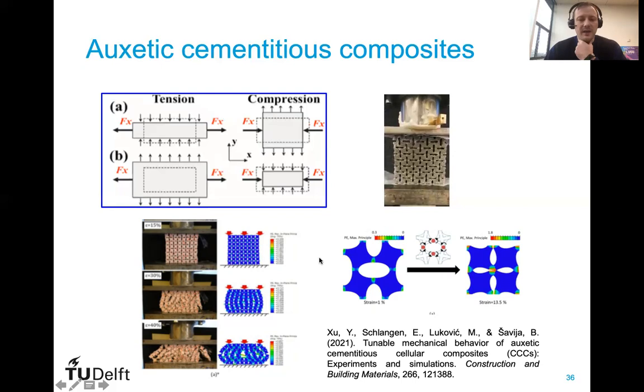So we used, again here, CDPM, first to simulate the deformation and fracture process of the material, but more importantly, we used the model to understand why and how we can achieve this auxeticity. What the model told us is that with elliptical shapes of these holes, we have stress concentrations at the tips of the ellipse. These stress concentrations cause microcracks that are then bridged by the fibers present in the matrix. And then they rotate. If we didn't use the fibers, the specimens would simply explode, which we also observed in some trials in the lab. So it is the fibers and the shape of the ellipses that allow this quasi-plastic behavior of these joints, and also the rotation that enables auxetic behavior of these materials. So this is very nice, that we can use models to explain behavior from the experiments.